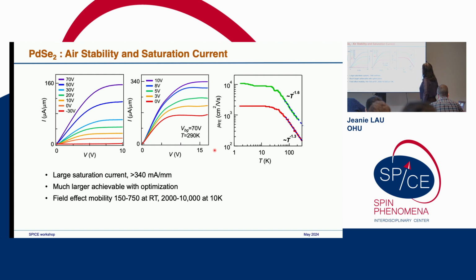It's about between 150 to 750 at room temperature, and between 2,000 and 10,000 at low temperature. And this mobility kind of follows this power law dependence, so it's probably limited by phonons, and then saturating, probably limited by impurities at low temperature.